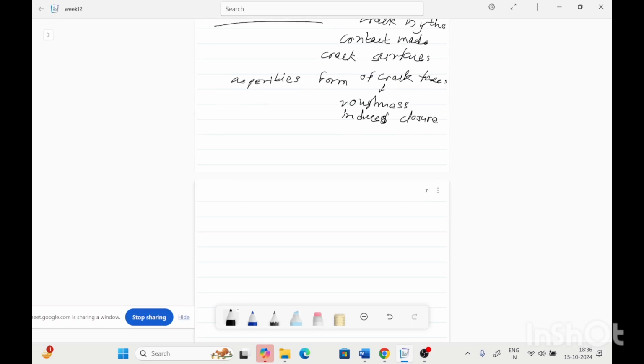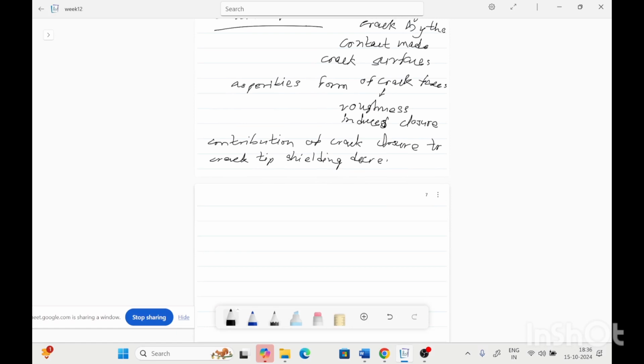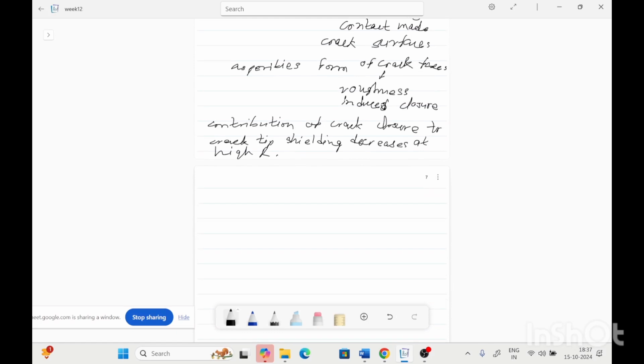So the contribution of crack closure to crack tip shielding decreases at high stress ratio. Means, because at high R the other phenomena will affect the crack growth rate.